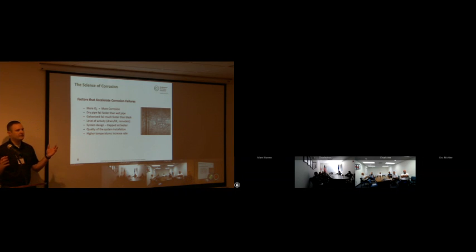We said, we got to looking, and we said, well, what's going on here? And what happened was that was where the lumber yard door was. That's where they drove the fork trucks through to load the lumber trucks. And we said, well, how often is this door open? They said, well, during business hours, it's open almost all the time. So we went and got a thermometer, and we measured the temperature as 60 degrees warmer in that bay than it was in the other 2 bays. And so that's what was causing that one to experience so much more corrosion.